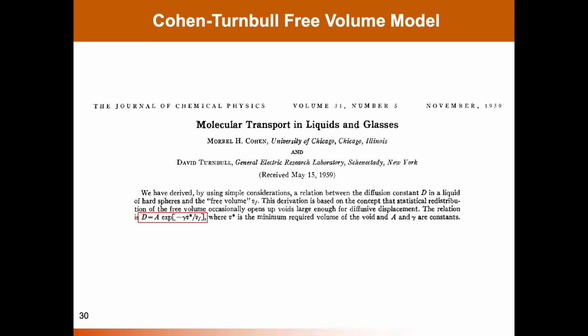It is that the diffusion coefficient is related exponentially to the size of the minimum required volume for these spheres to execute a diffusion step. This we're going to associate with penetrant size, okay? And so it says that the bigger the penetrant size, the lower is the diffusion coefficient. That qualitatively is what we observe in practice. And VF is the free volume that is present in this liquid of hard spheres.